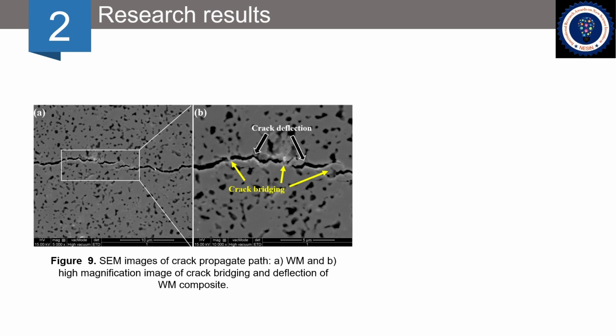The deflection has been reported to mainly depend on the particle morphology and the percentage of the reinforcing phase. It can be seen from Figure 9 that magnesium oxide is dispersed in the tungsten carbide matrix. When the crack propagates near the edge of magnesium oxide, the crack will deflect and propagate in a zigzag path, leading to the dissipation of fracture energy. If the crack propagates around the magnesium oxide center, crack bridging will occur. The increased crack bridging is a more effective mechanism for promoting toughness.